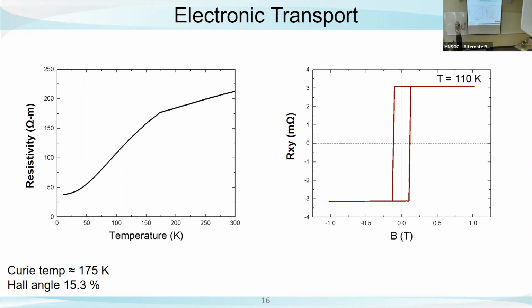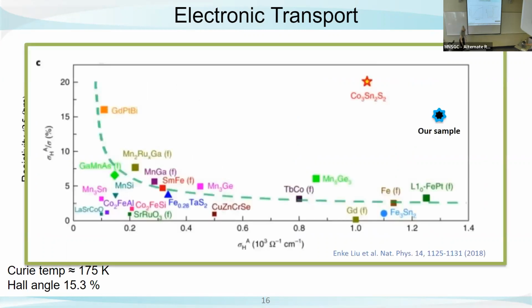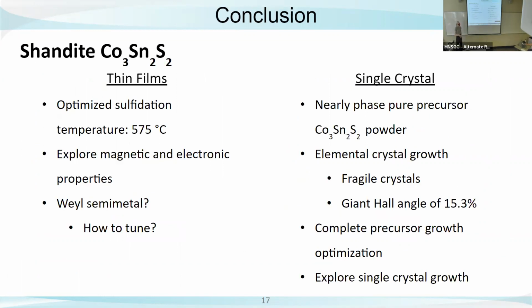And then we can take that Hall signal and calculate a Hall angle. And when we compare that Hall angle with the other data, we see that our sample is just like the other one. We get that giant anomalous Hall effect from our sample. It's not perfectly where previous studies have shown, but it is off the curve, which is exactly what we wanted to see. So it gives us some hope for the future.